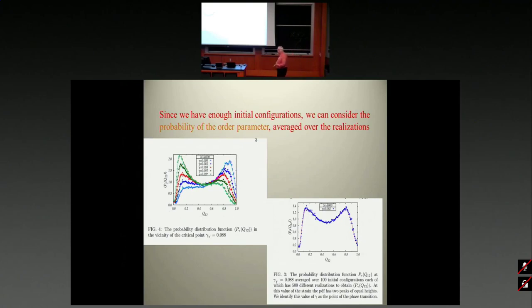But then you can ask me, wait a moment, you were looking for an understanding of an increase of correlation length. System spanning, shear band. A first-order transition generically does not have an increase of correlation length. But now I want to point out to you the green curve. You see the green curve here? So this is slightly after the first-order transition. You have here a flat region.